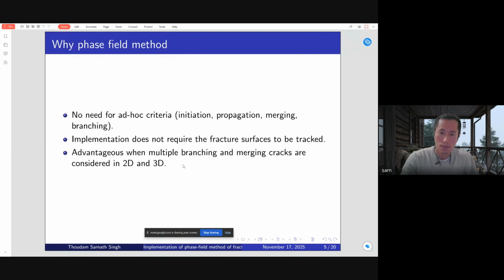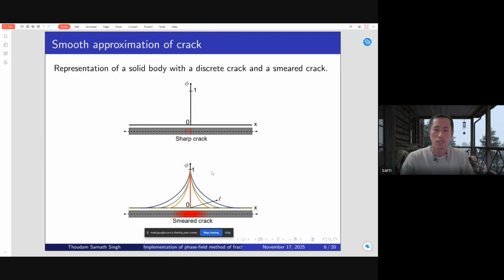Now let's look at what the smooth function is. As I said earlier, in a sharp crack, this rod has a sharp crack at its center, and this is represented by using a sharp function or a discrete function, like this kind of function. And in the case of a smeared crack, or the smooth crack, the crack is diffused into the surrounding region. The damage is sort of diffused into the surrounding region. Such damage is represented by this kind of function, where there is a smooth transition from phi equal to 0 to 1. And this is the point where the crack is located, but because it is diffused, this is the crack region.